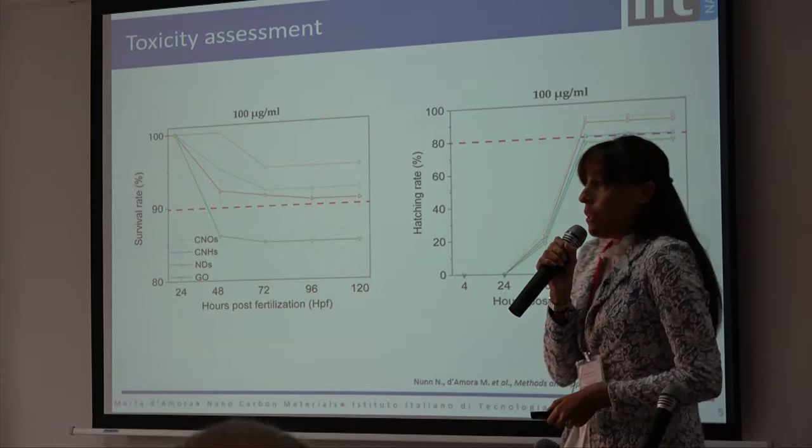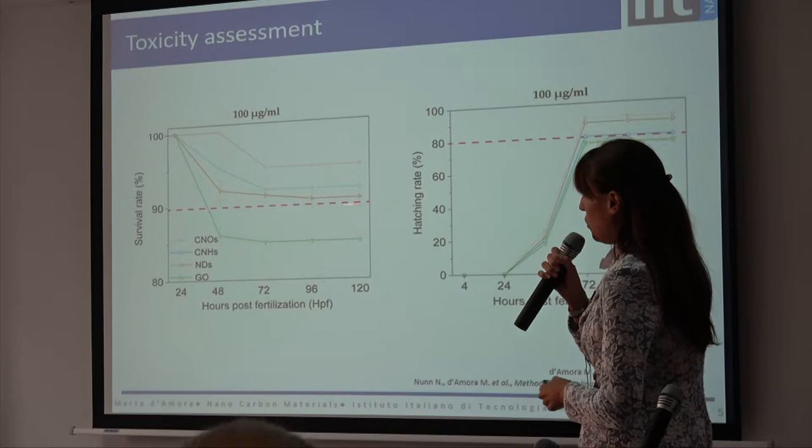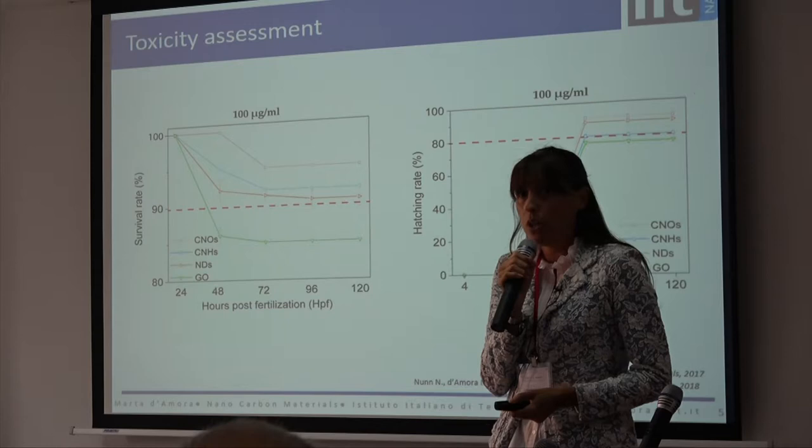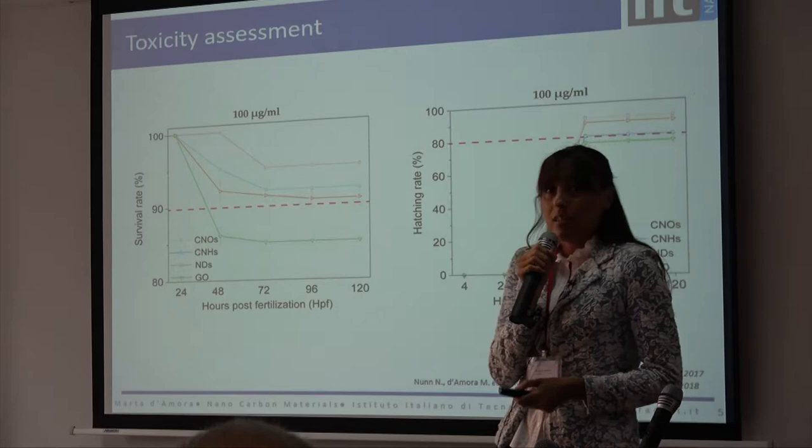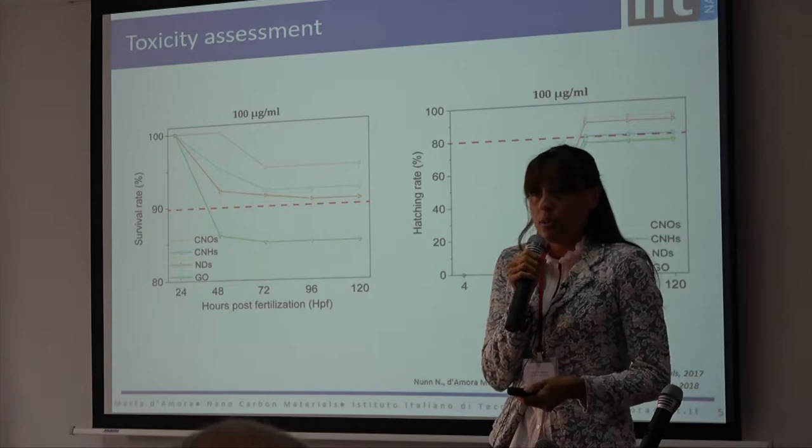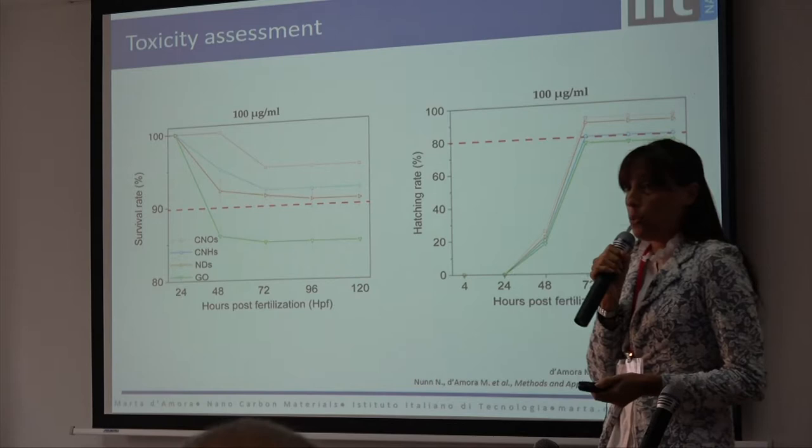In conclusion, our results report that carbon nano-onions, carbon nanohorns, and nanodiamonds present a concentration-dependent behavior on zebrafish, with no detectable toxicity on this vertebrate system. On the other hand, graphene oxide induces high toxicity with a consequent developmental delay, as you can see from the plot.